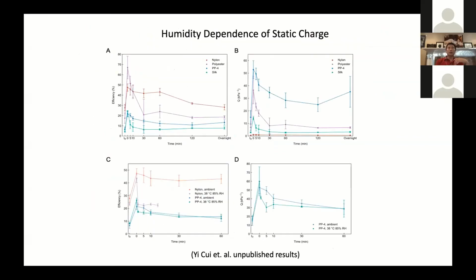And then we also compare A and B on the top. If you generate static charge, your filtration efficiency can be increased a lot, but how long can it last? Nylon, polyester, polypropylene and silk, they can hold it for quite long. You look at the data. This is an ambient condition. You can wait overnight, they look fine, particularly nylon and polypropylene. However, if you're in a humid condition, if you use it for a facial mask, you're going to breathe out a lot of moisture right there.